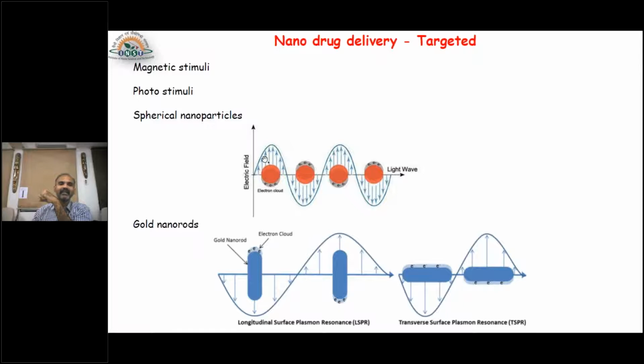When you have some drugs around these particles and a polymer that is thermosensitive, you send this cargo inside your blood, and it will just circulate as an inert particle. Then when you shine a monochromatic light of 520 nanometers on it, the surface plasmon happens, and then the oscillation happens. The energy needs to be given out, and it will be given out as heat, and the thermosensitive polymer will rupture, and the drug will be released.